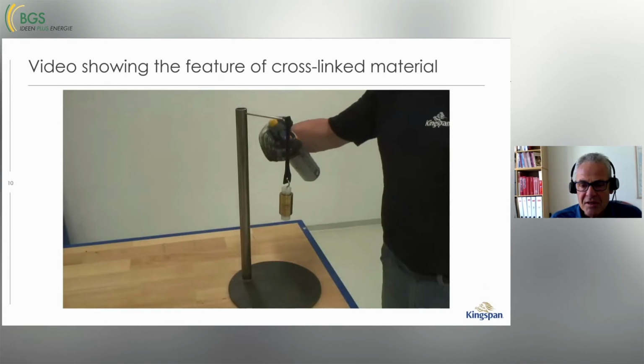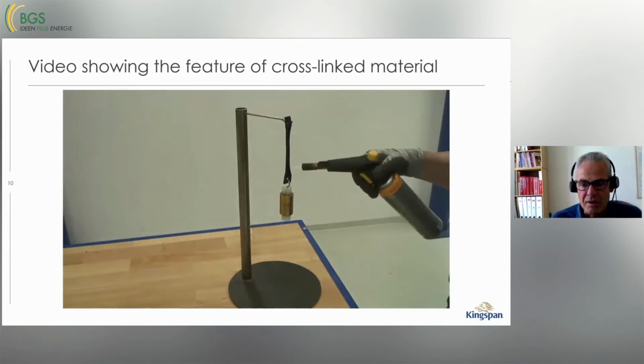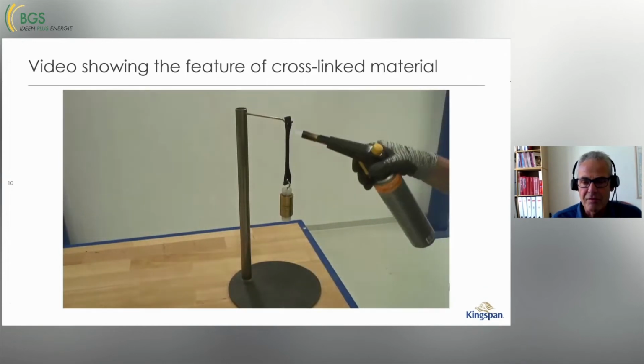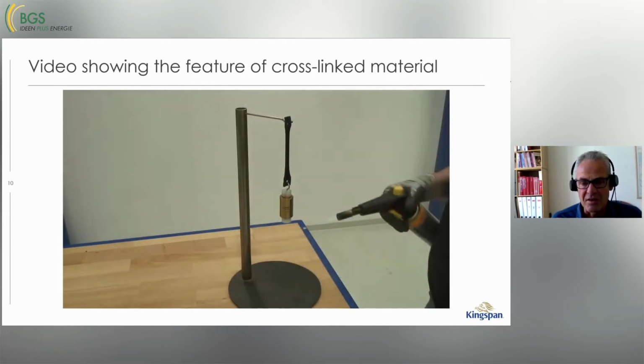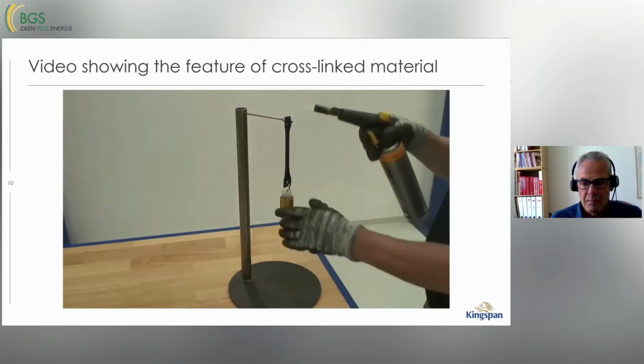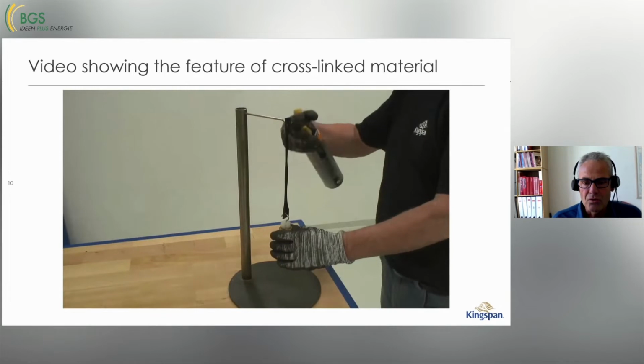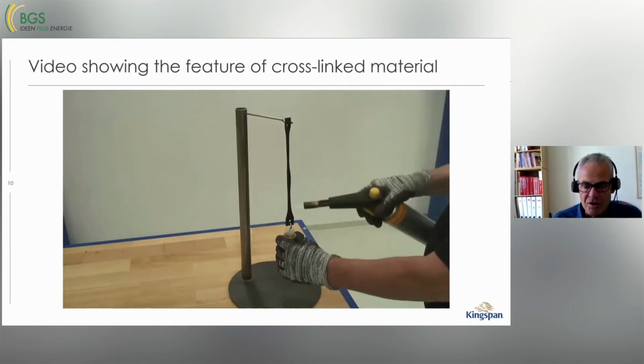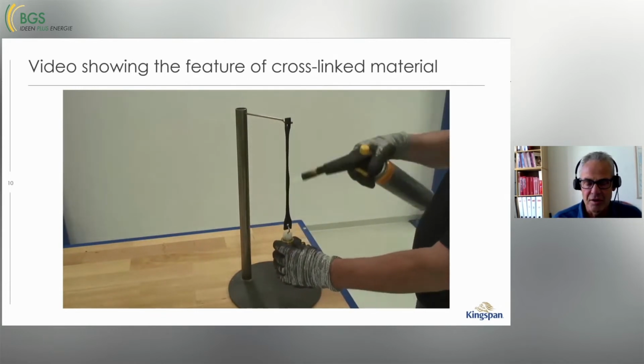Then we do the same test, but now it's with cross-linked material. And the geometry of the test piece is exactly the same. After heating it for some time, it shows it will not break. And we continue heating it, and we stretch the material.